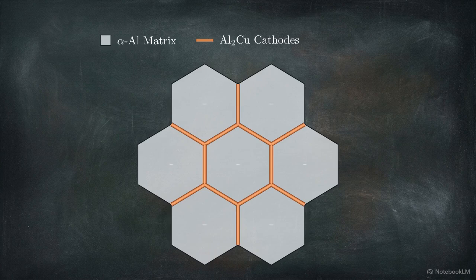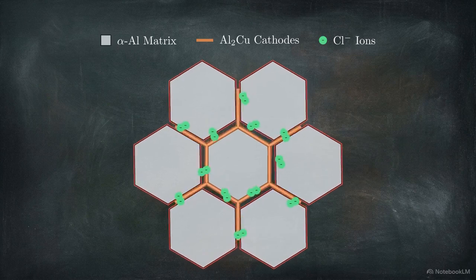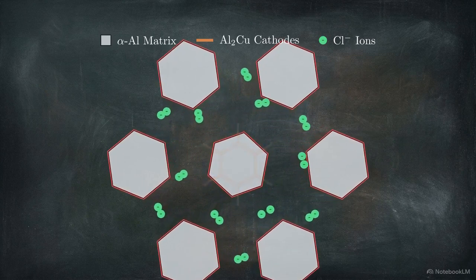High copper concentration creates localized cathodic sites. These boost the anodic activity of neighboring pure aluminum, turning the matrix against itself. Here, halide attack accelerates. Mobile chloride ions target these charged interfaces, unzipping the hardened grain structure from inside out.